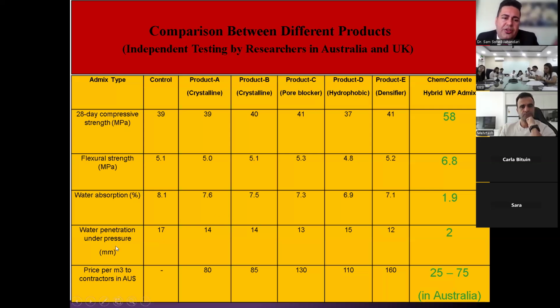In terms of water penetration under pressure, the control one was 17 millimeter water penetration depth in the concrete sample. For the crystalline it was 14, 13, 15, 12. But in case of our product, it was only 2 millimeter. And yeah, the price per cubic meter here in Australia's market, at the same time, the good thing is that for the end users or contractors, the price per cubic meter of our product is almost 3 times cheaper, 2 to 3 times cheaper than the other similar products on the market.